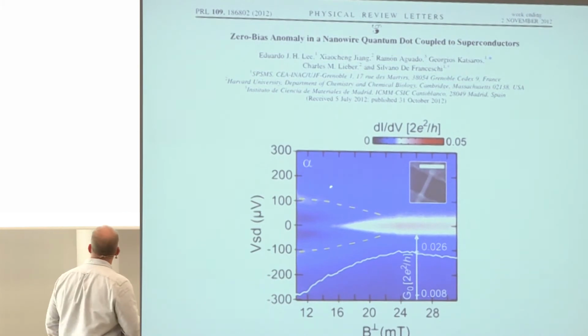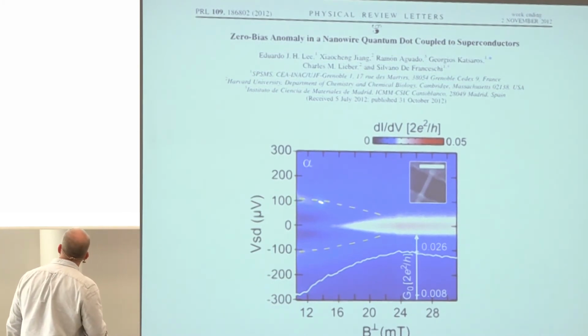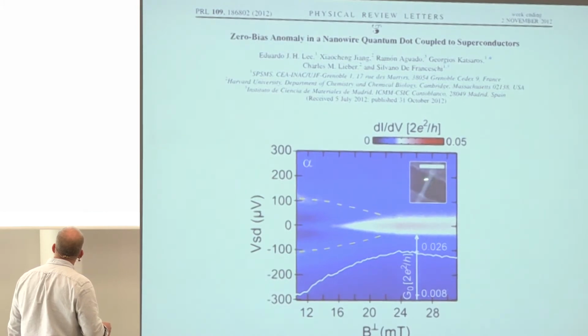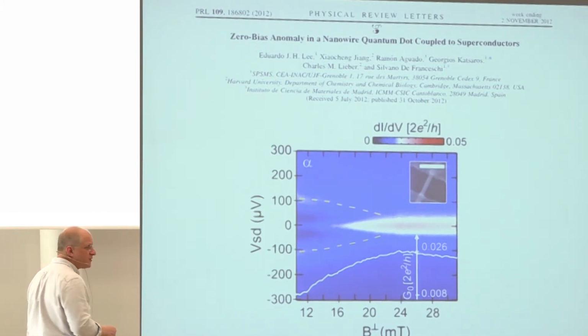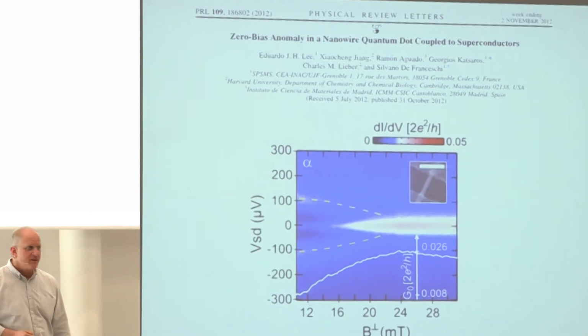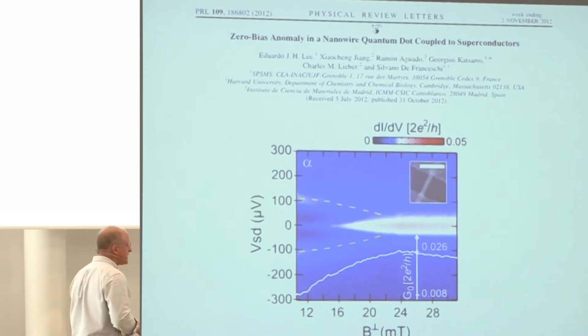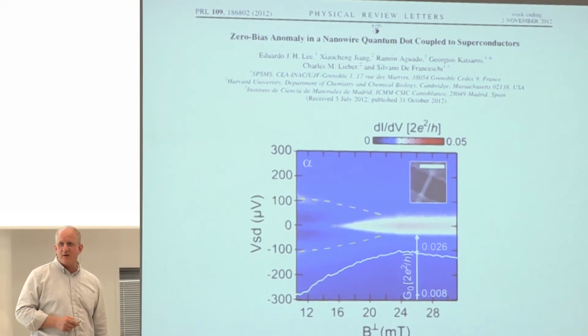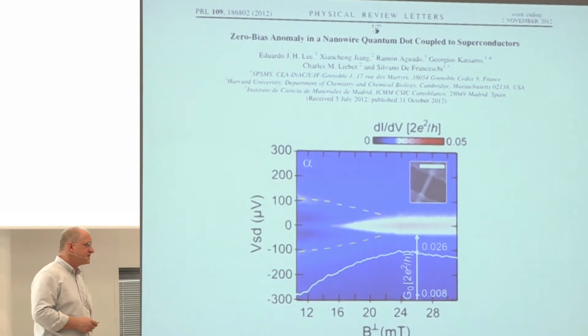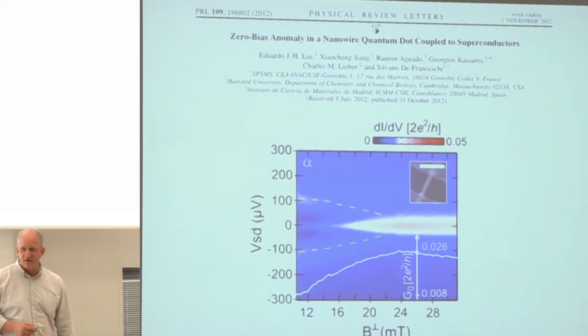Here's an example of something in which you can see, it's a little bit hard to see on these data. Here's something that looks like a BCS density of states ridge. This is in an indium arsenide nanowire, the same material. Now there's two superconductors on the two sides. You turn up the magnetic field and bango, this gigantic zero bias peak shows up. And I can tell you that this zero bias peak has nothing to do with the presence of a Majorana state at the end, because it persists long after the destruction of superconductivity.